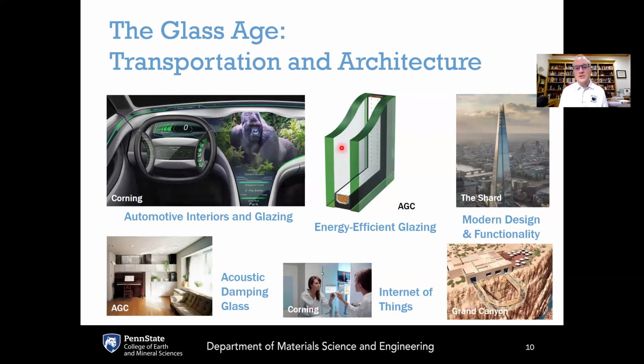The next generation is what's called a vacuum insulated glazing, where instead of having a noble gas between the 2 panes, there's literally nothing in between the panes. So they pull a vacuum. So the only way then to transmit heat would be through radiation, since there's no gas particles in between. This creates a mechanical stress on the glass, so the long-term mechanical fatigue behavior of the glass becomes critically important.